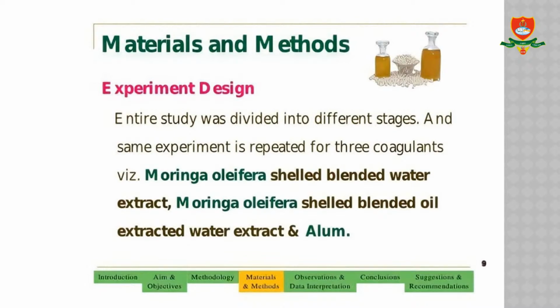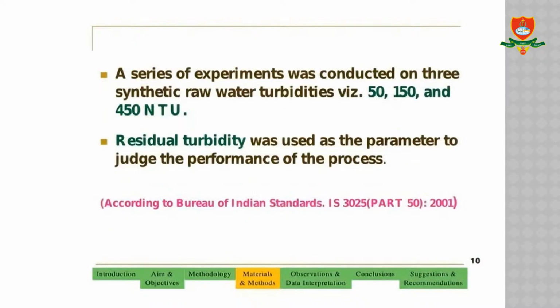Materials and methods: our entire study was divided into different stages, and the same experiment was repeated for 3 coagulants: Moringa oleifera shelled blended water extract, Moringa oleifera shelled blended oil extracted water extract, and alum. A series of experiments was conducted on 3 synthetic raw water turbidities: 50, 150, and 450 NTUs. Residual turbidity was used as a parameter to judge the performance of the process.